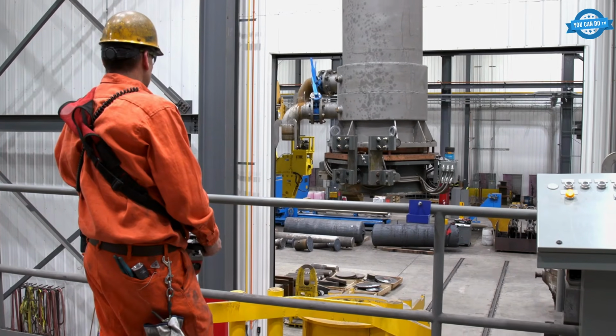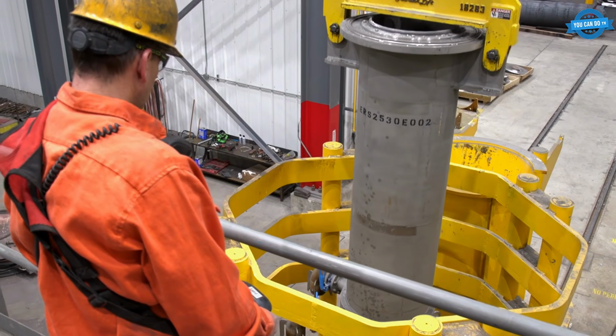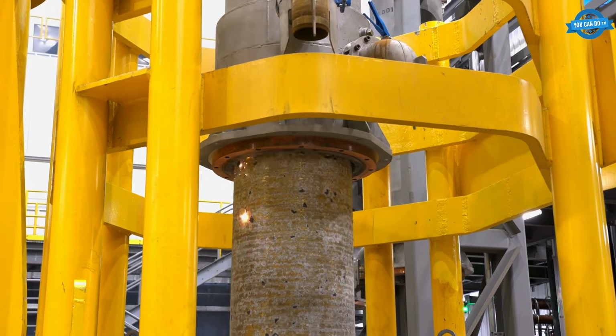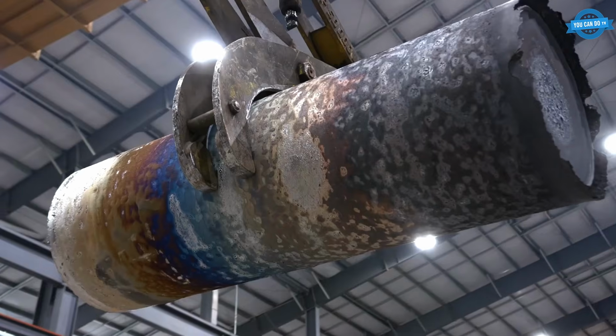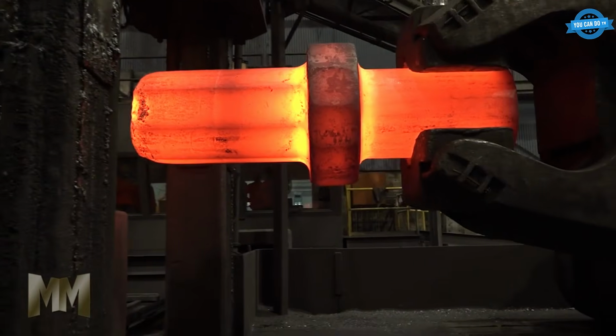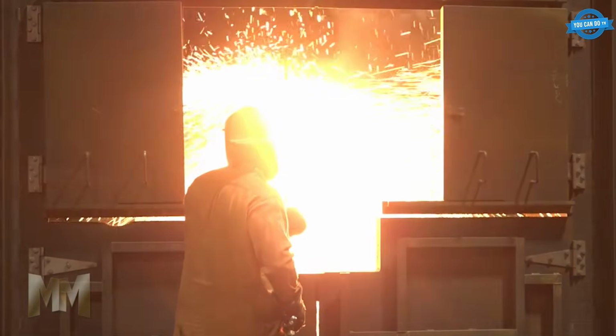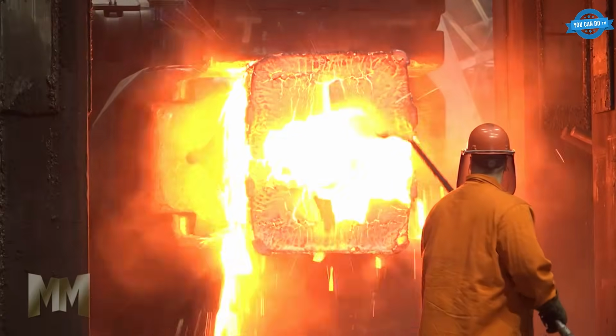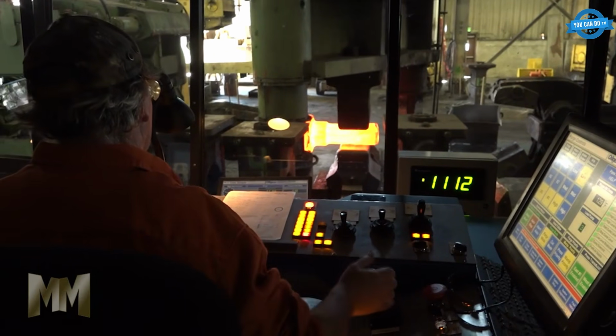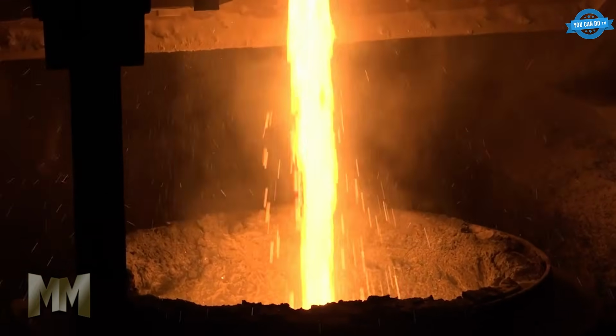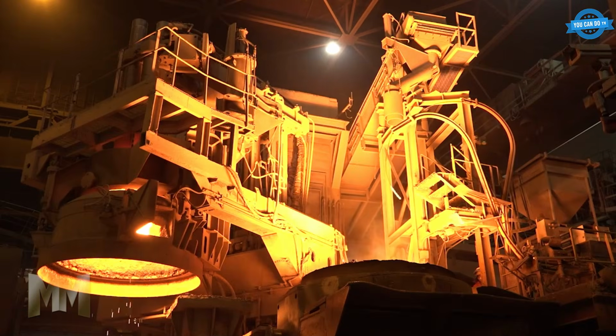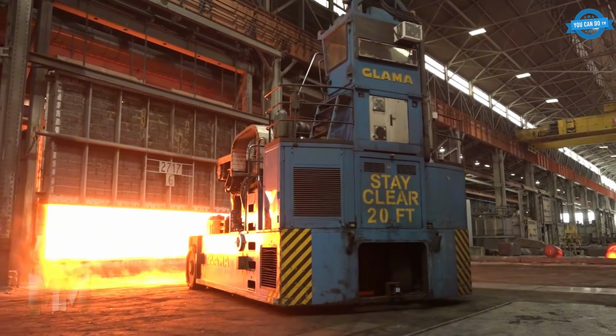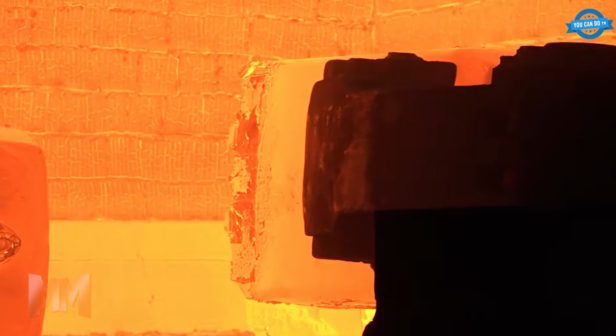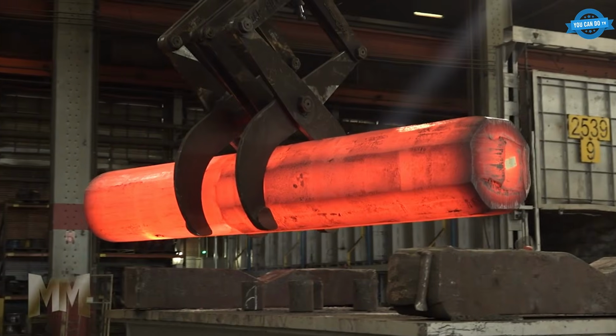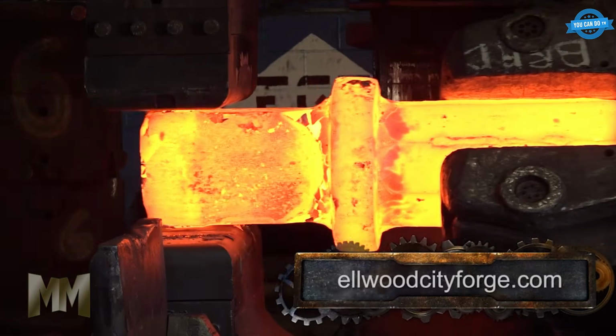The electroslag remelt furnace, the largest of its kind in the Western Hemisphere, runs each ingot through liquid slag drop by drop, removing the large inclusions that forging would otherwise turn into elongated weaknesses. The real work of forging is not making the part smaller, but making the inside of the metal harder to tear apart. An open die forging operation runs 5 presses, up to 5,000 tons of force, capable of handling forgings up to 110,000 pounds, 57 feet long, and 94 inches across.